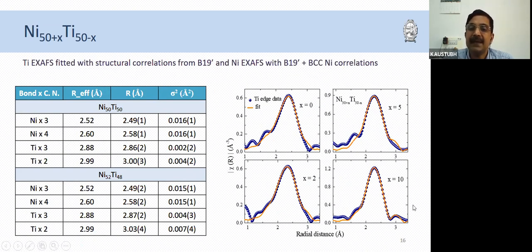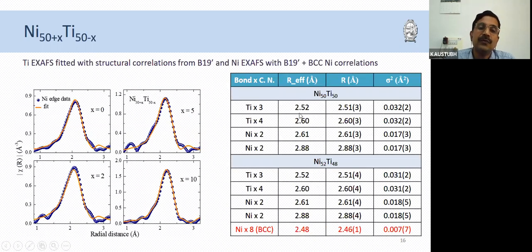This is for the titanium edge, and the parameters matched very well with the expected values. And for nickel also, we could do the same thing, and we could get a very good fit as well as good parameters, except that we had to introduce this nickel-nickel correlation at about 2.48 angstrom, which is coming from the body-centered cubic phase.